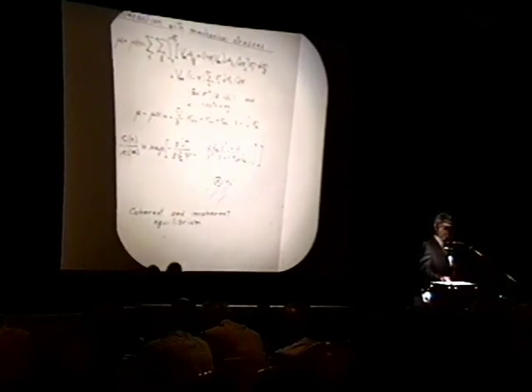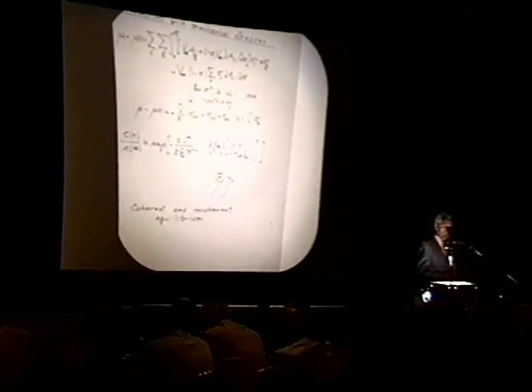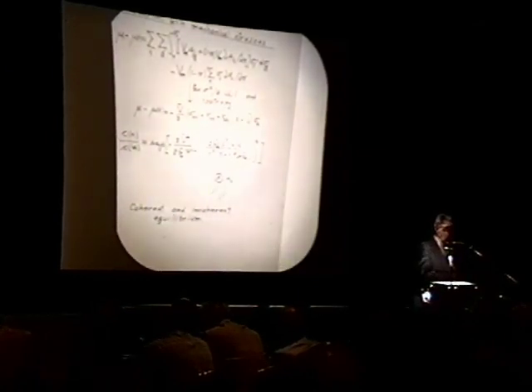In the case of something like the beta phase of palladium growing inside of the alpha phase, this sort of equation is not sufficiently complicated. It is a much more complicated equation that is developed. But in that case, you have a similar thing. You will have an enhancement of concentration out here and a spatial variation.